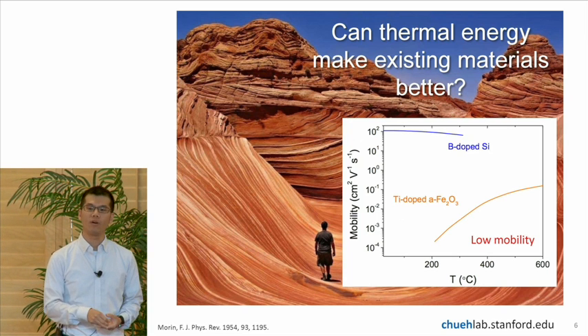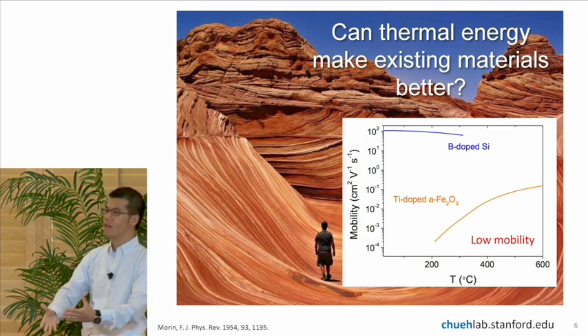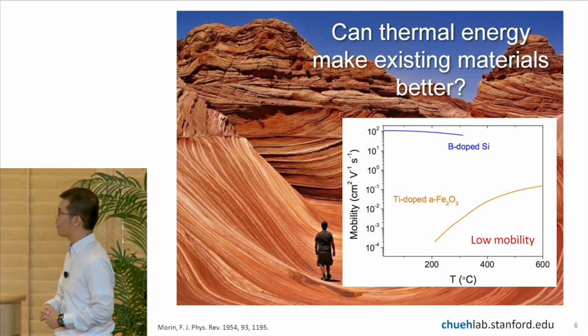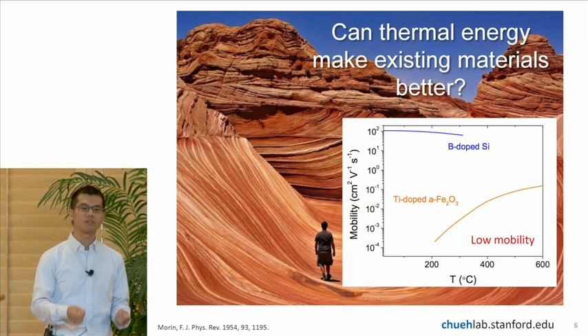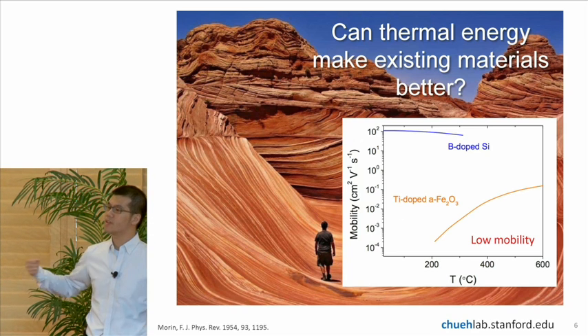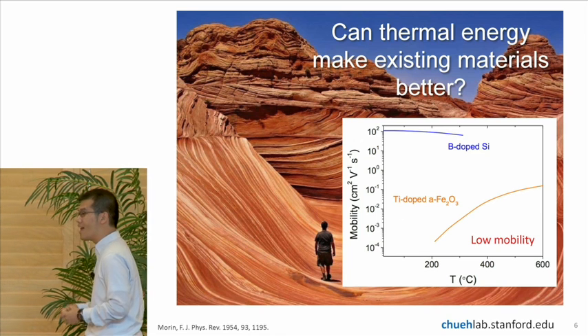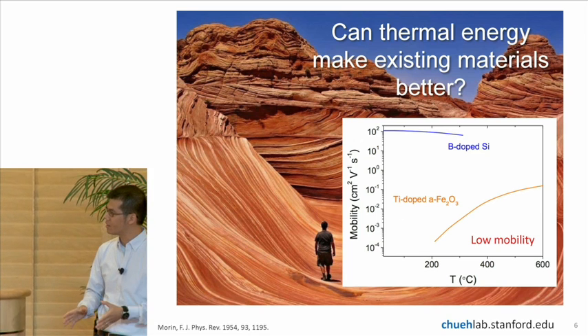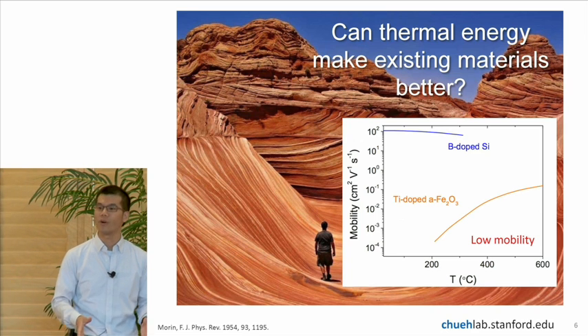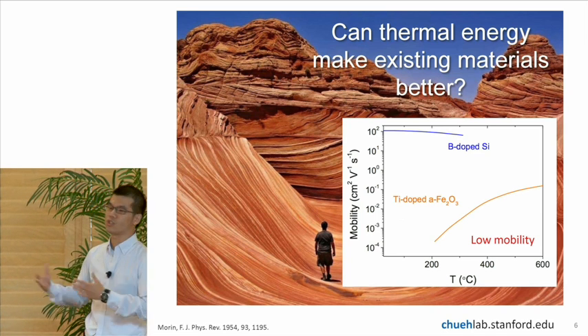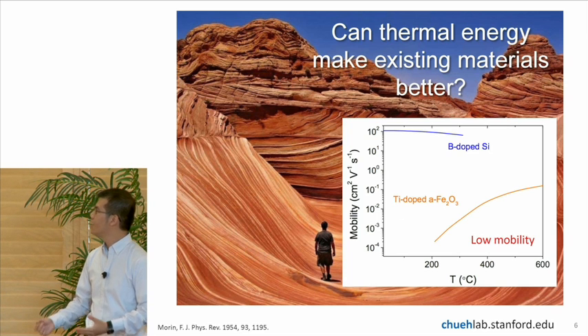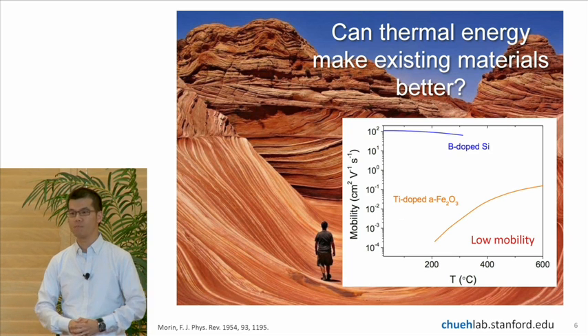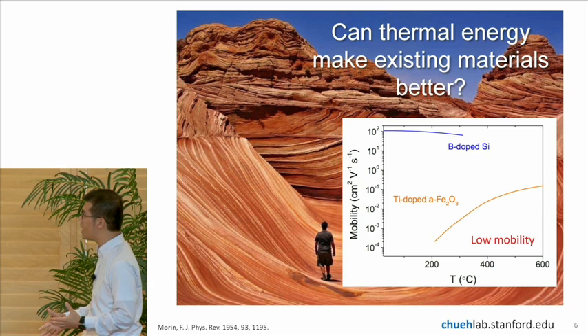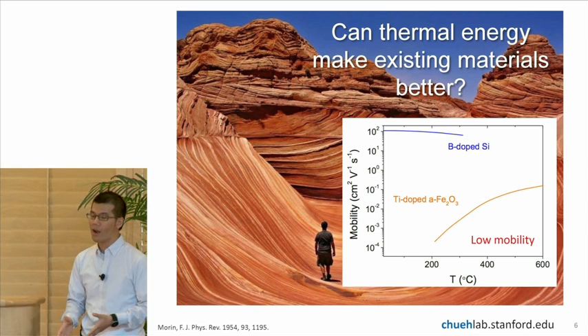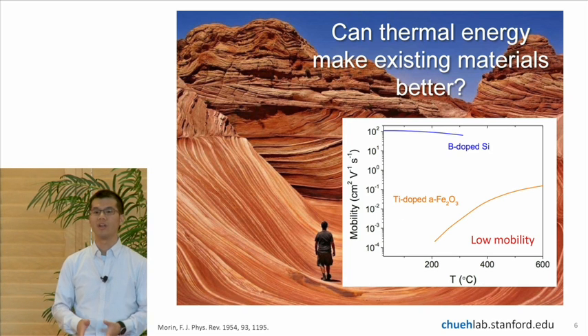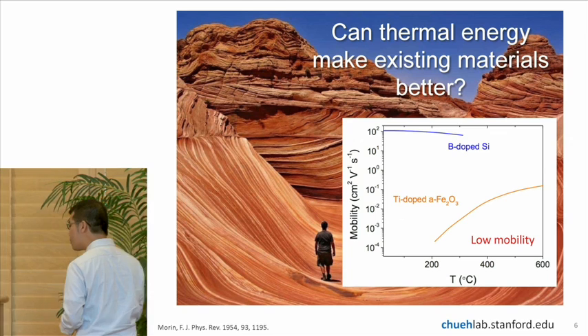So here we propose that increasing the temperature, which comes from the incorporation of thermal energy into photoelectrochemical cells, you're able to increase the minority carrier mobility so that you can separate the charge better in the photoelectrochemical cell. I should note there are very few routes you can envision by which you can improve the mobility of a minority carrier in a semiconductor. You can think about doping, but that just increases the concentration of the majority carrier. There is not another route. If you nanostructure, that's fine too, but again, you're not changing the mobility. So the fundamental limitation of these highly stable, abundant materials like iron oxide is simply that the mobility isn't good enough at room temperature. So let's up the temperature and see what happens.